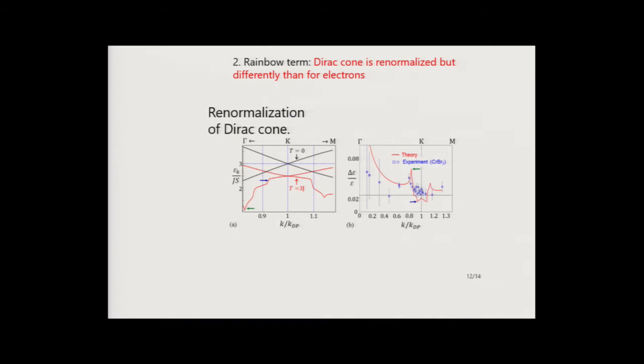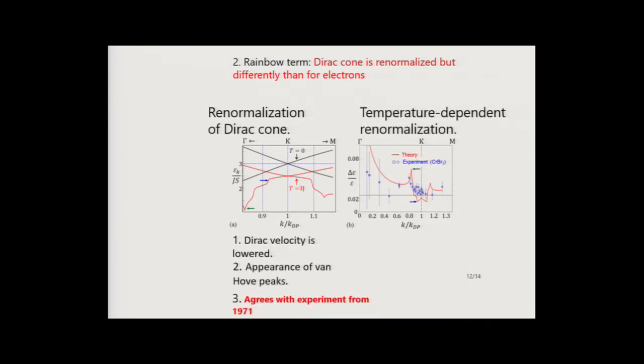So when we apply the theory of interaction of these magnons to this Dirac point, we find two things happening. One, the Dirac crossing point drops down, and the other is that the dispersion curve for the interacting bosons flattens out. Now, if you remember, in the case of the fermions, with the Coulomb interaction in graphene, in the vicinity of the Dirac point, interaction leads to the velocity stiffening up. For interacting bosons, we find that short-range interactions lead to a flattened dispersion. And so we were able to explain some of the signatures seen in experiment.